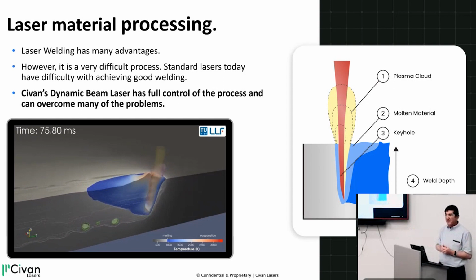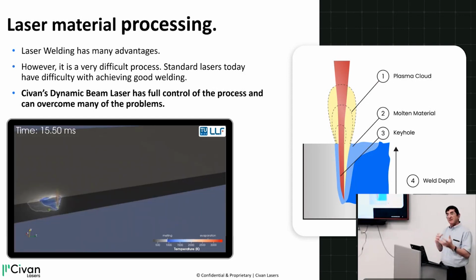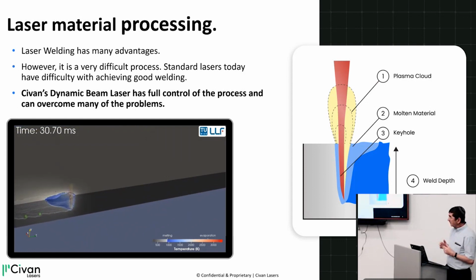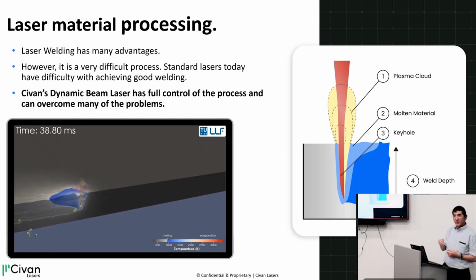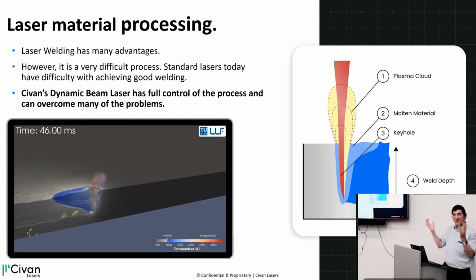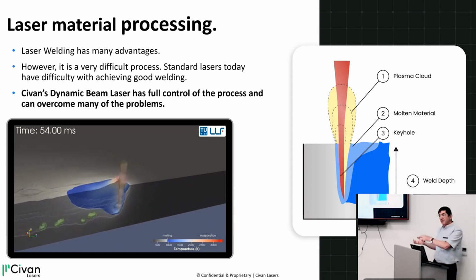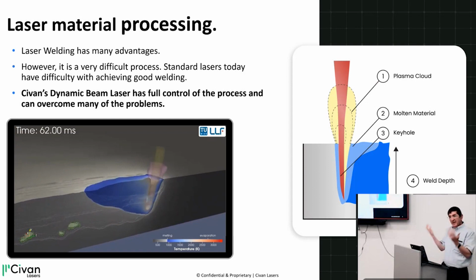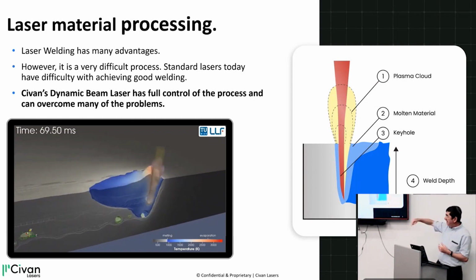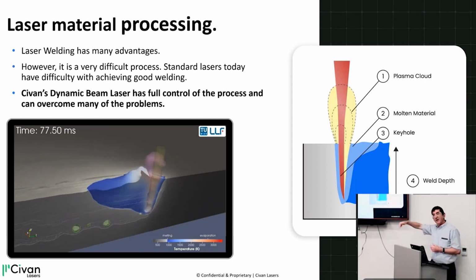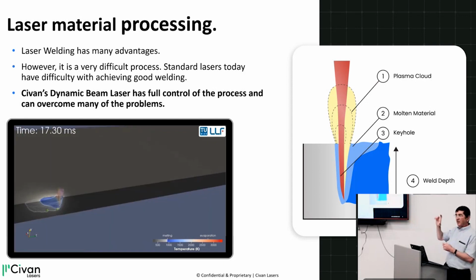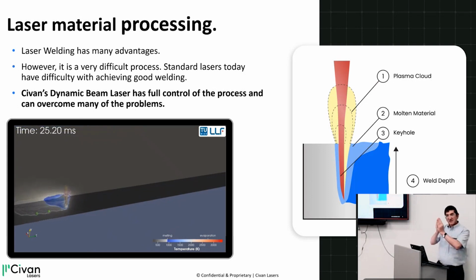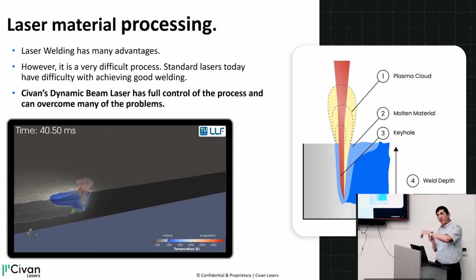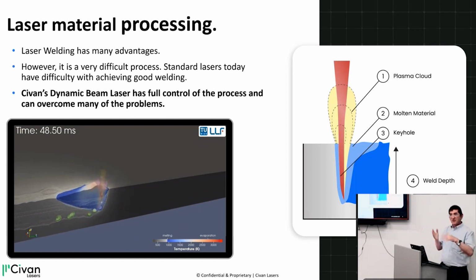And that sounds great. The problem is that the same things that are the advantage of the laser are also the disadvantage. It is happening so fast that it's completely uncontrollable. Because think that in 1 millisecond or a few tens of milliseconds, the material goes from solid to liquid to gas and back, so you can't control the process. And the whole thing is propagating at 100 or 500 millimeters per second. And you have this keyhole, which is basically gas with high pressure, but around it, you have liquid metal. And the liquid metal always wants to fall into this keyhole. So you have what's called keyhole instability.